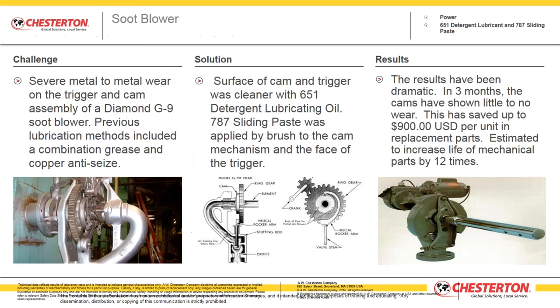on poppet valves. So here's a case history on these Diamond G9 soot blowers, where we're lubricating the ring gear, crank, and poppet valve with a product that we have. We first clean the material with our 651 detergent lubricating oil to remove contaminants, and then heavily lubricated with a graphite and molybdenum based grease, which is our 787 sliding paste. And we can see here that estimated increase in service life of these soot blowers was up to 12 times.